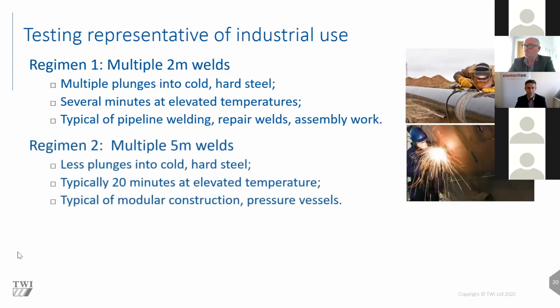The second testing regimen that we've been looking at is doing multiple 5-meter long welds, which are probably typical of many kinds of general engineering and modular construction. This requires fewer plunges of the tool into the cold steel, but it does see much longer times at elevated temperature, typically 20 to 25 minutes, soaking there at over 1,000 degrees.